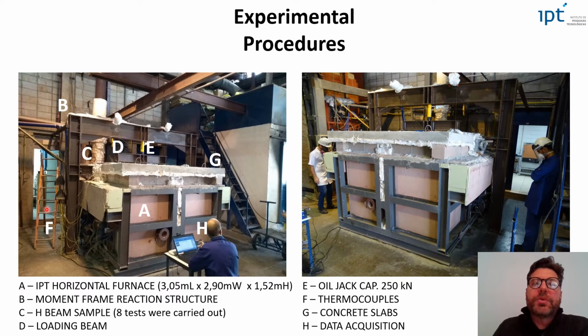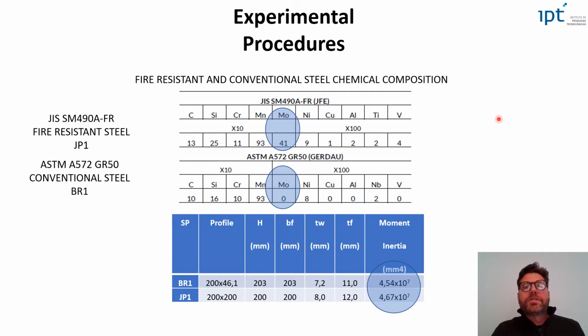Thermocouples were installed in three different sections of the samples, and also inside the furnace atmosphere nearby the samples. In order to not allow the heat to escape and let the beams be free to bend during the loading, three precast concrete slabs were installed above the top flanges. As I explained, two different steels with different chemical compositions were used, allowing us to compare the behavior of both steels under the same thermomechanical loading situation.